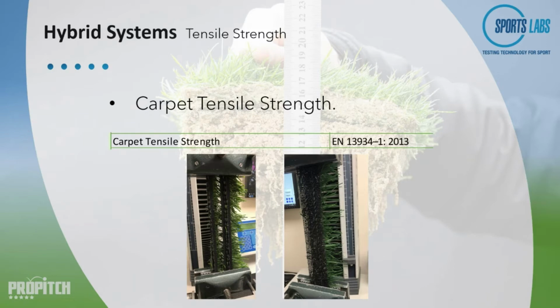Test specimens are prepared from both directions of manufacturing, the warp and the weft directions. The maximum percentage difference between the two directions is then calculated. This value would need to be within any set requirements. The tensile strength in both directions that we've currently recorded in hybrid systems can vary a lot depending on the type of construction. The testing can also be carried out on unaged and aged test specimens to also assess any potential loss in strength during time and use.